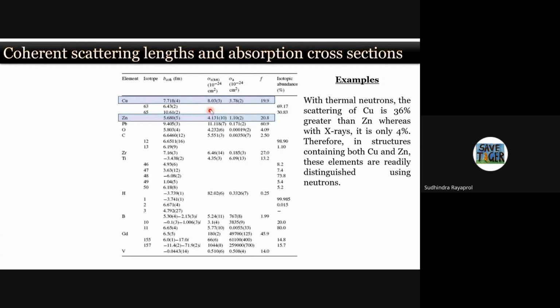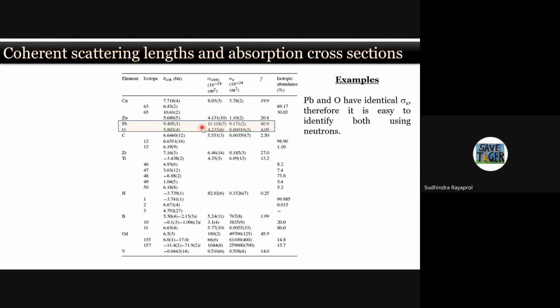For a good scattering from neutrons, your scattering cross-section should be higher than the absorption cross-section. If you look at the example of lead and oxygen, the lead is the one which is dominant over the oxygen in the case of X-ray form factors. Whereas in the case of neutrons, the coherent scattering lets you easily distinguish between lead and oxygen. You can determine their presence. And in terms of the cross-sections, the scattering cross-section for lead and oxygen is much higher than their absorption cross-section.